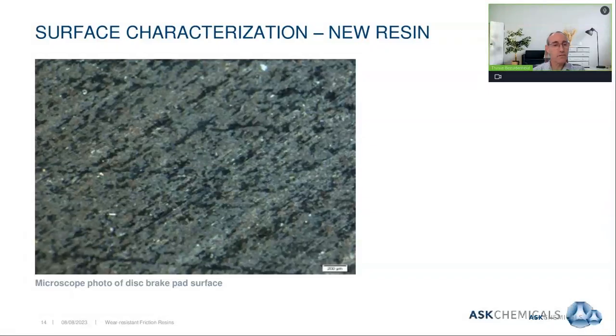Again, same size surface of about a 3 millimeter cross section. Immediately you can see a difference in the degradation behavior of the surface being much smoother. The surface remains intact or more intact. And this refers directly to the degradation behavior of the matrix, or the binder holding the matrix together much better.